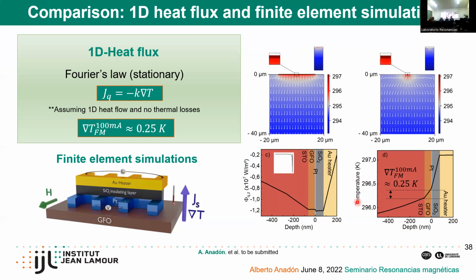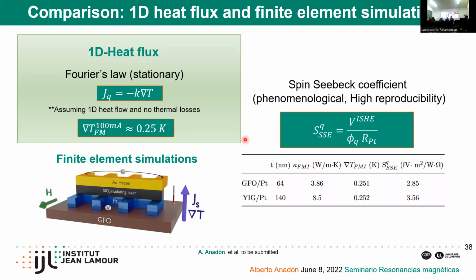So we can look at the temperature profile, and we can calculate from this simulation how much is the temperature gradient in our magnetic system. And basically, what we observe is that our first guess estimation was mostly correct. So we can compare using this simulation, in addition to the one in yttrium iron garnet, the spin current generation from thermal origin in both systems.